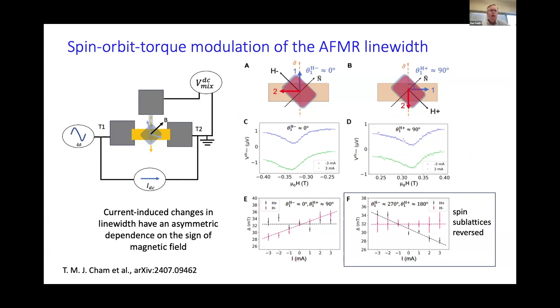We're working here in analogy with spin-orbit torque in ferromagnets. In ferromagnets, you see that a spin-orbit torque can change the resonant line width of a ferromagnetic resonance when the spin due to the spin-orbit torque is parallel to the precession axis of the magnet. And we've seen something similar here with the antiferromagnet.